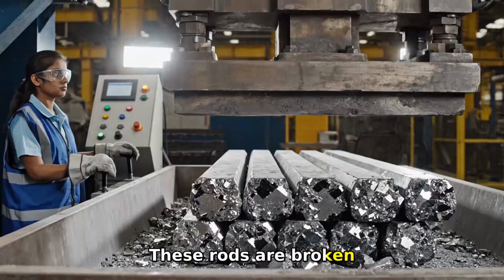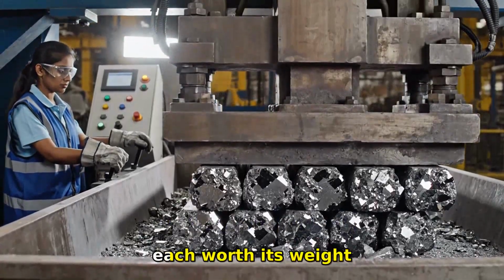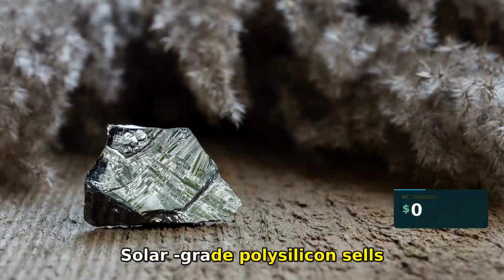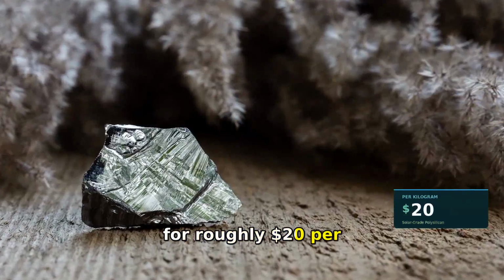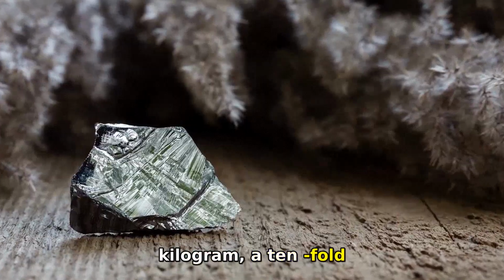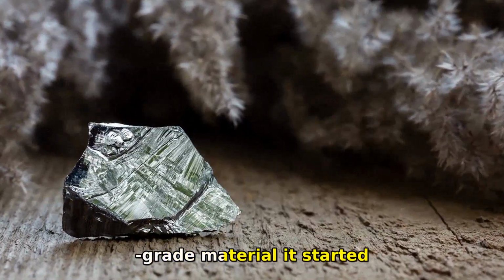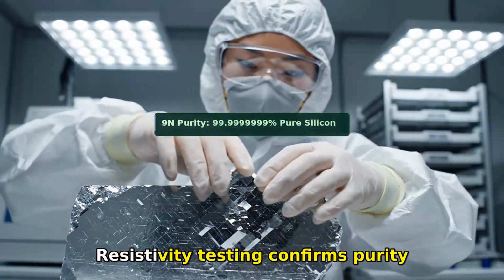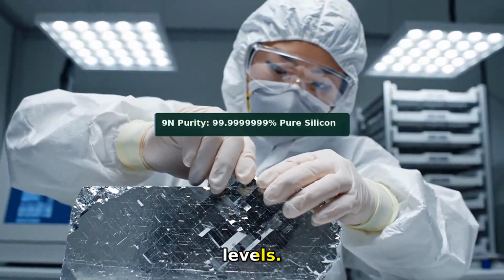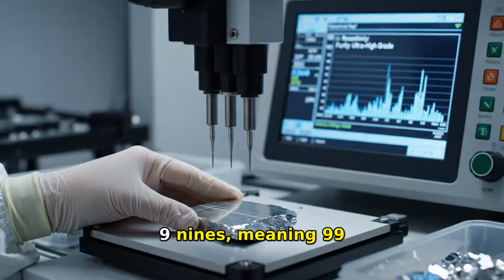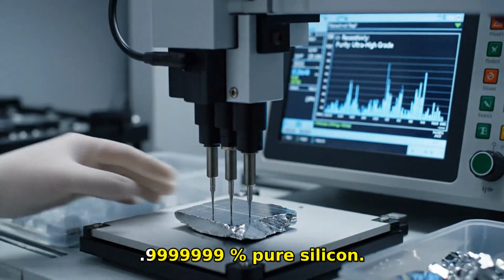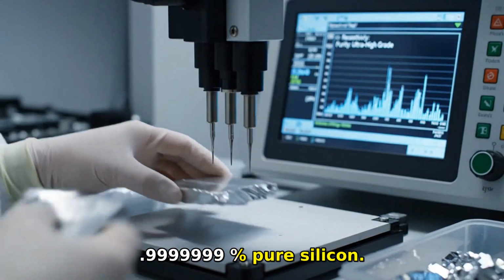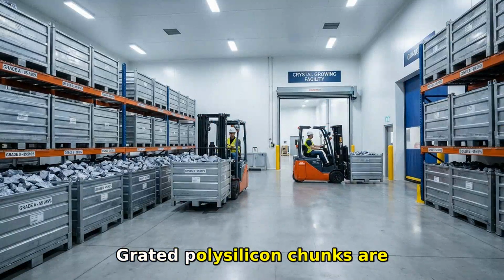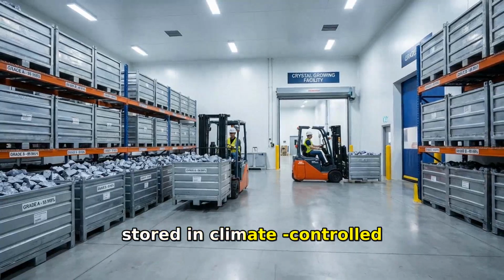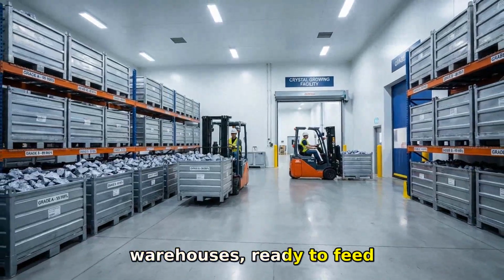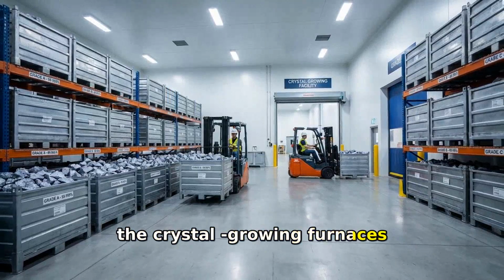These rods are broken into fist-sized chunks, each worth its weight in silver. Solar-grade polysilicon sells for roughly $20 per kilogram, a 10-fold markup from the metallurgical-grade material it started as. Resistivity testing confirms purity levels. Each batch must reach 9 nines, meaning 99.9999999% pure silicon. Graded polysilicon chunks are stored in climate-controlled warehouses, ready to feed the crystal growing furnaces next door.